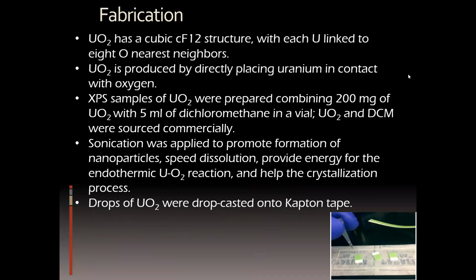So he fabricated the uranium samples. He bought uranium dioxide commercially. And he also used dichloromethane for the processing, also commercially, and then he mixed them and formed the samples by sonication, waiting for the whole thing to dry. He dropped them onto Kapton tape. This is Kapton tape, and that's the one that you use for SEMs, TEMs, and for my device. And then we analyzed this.